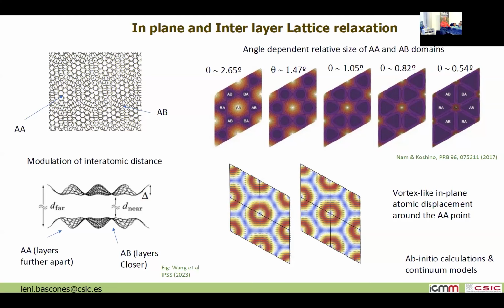Well, I think the main thing is associated with the fact that your stacking is modulated in real space. So somehow you are going from having, let's say, an AA stacking to an AB stacking, and so the system has to adjust. When the angle is small, the AB stacking is energetically more favorable, so the system has the tendency to move a bit into that configuration. The movement within the layer should be orders of magnitude smaller than the lattice constant. What I say is that this movement is not huge, but it's there.